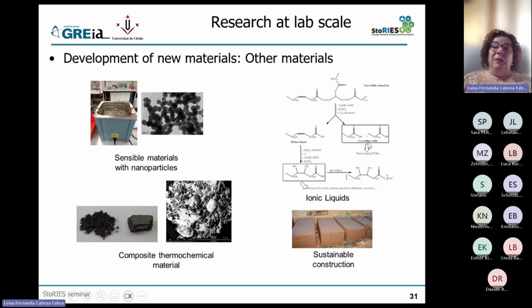One of the examples of developing new materials in our lab at the University of Lleida is that a few years ago, we worked with the chemistry department where they were producing ionic liquids, and they asked us to see if they could be good PCMs because they saw that they were materials that undergo the solidification-liquid phase change. And we measured them in the lab, and we were very impressed because we were able to produce some PCMs that had very, very, very high melting enthalpy. And when I say very high, it's 4, 5 to 10 times higher than what is a normal PCM.